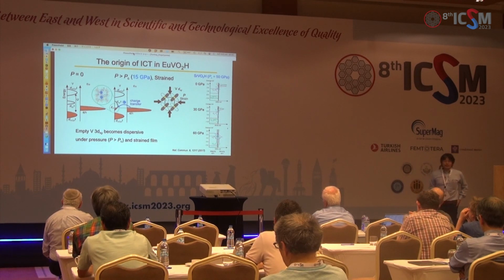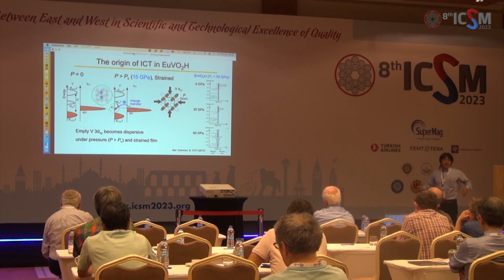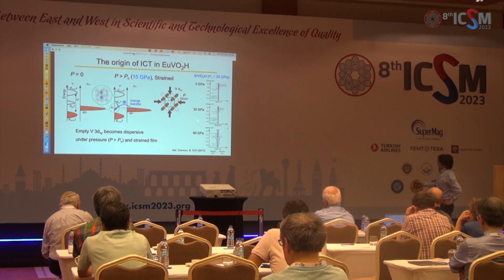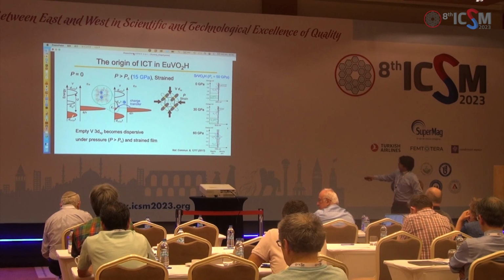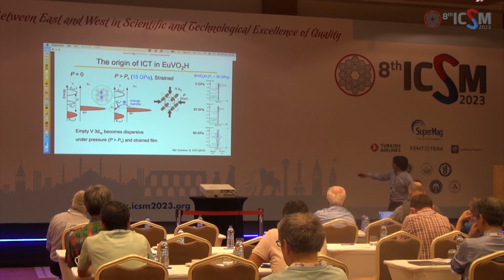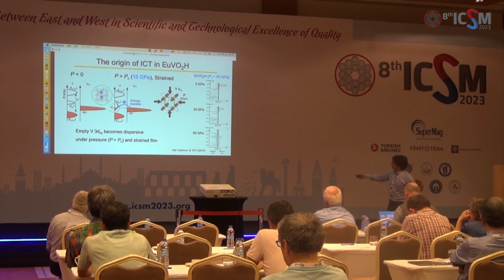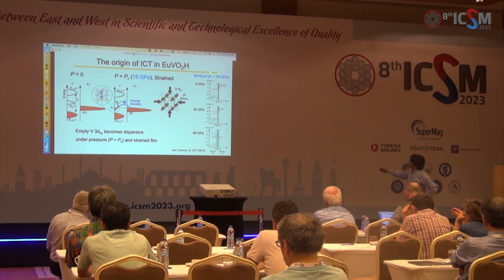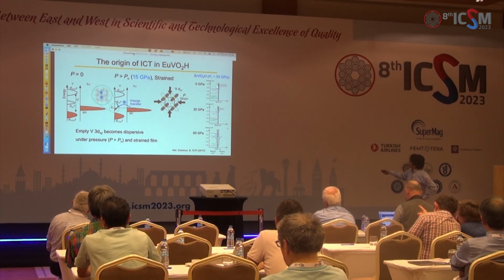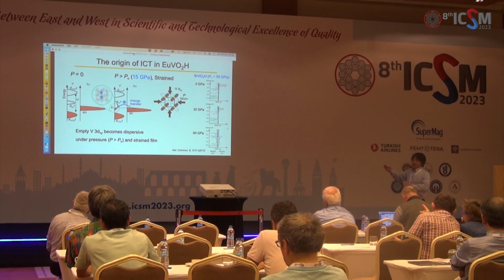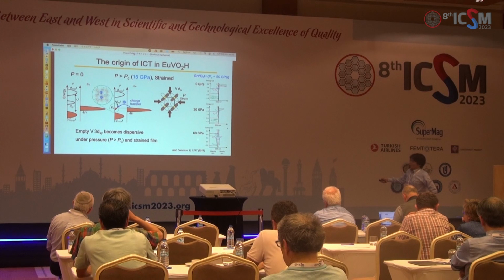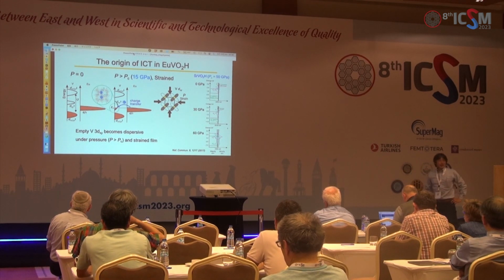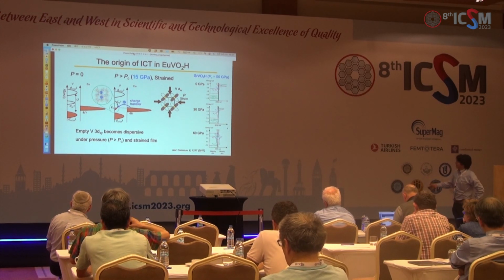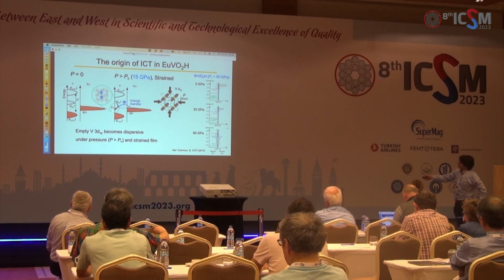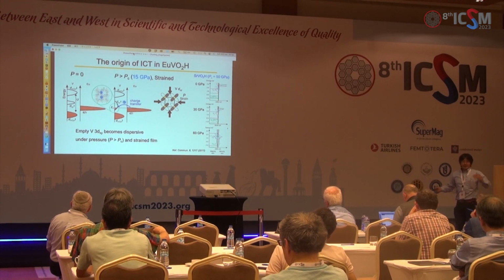And this view is also supported from our previous report on vanadium dioxide (VO2). We did the high pressure resistivity measurement, and we observed the Mott insulator to metal transition because of this dispersive empty orbital touching the ground state, the Fermi energy. Then, as you can see, this band becomes melting. So this is the calculation using DFT. You see the dxy orbital become significantly dispersive and finally at a pressure of 60 GPa, the Mott insulating state is destabilized to change into a metallic state. But in this case, before we arrive at this state, the charge transfer occurs, so metallicity appears earlier.